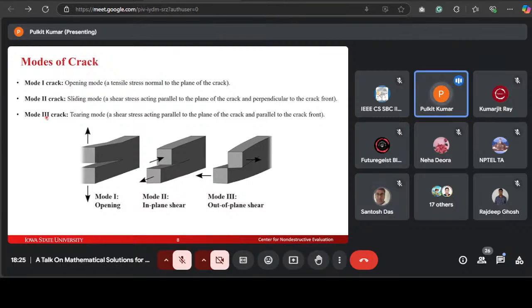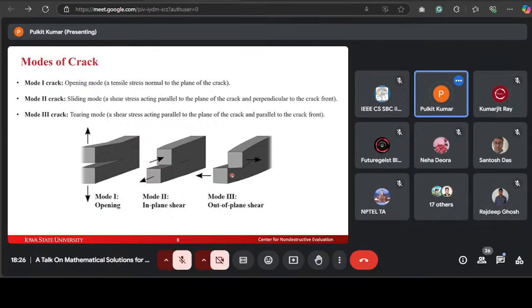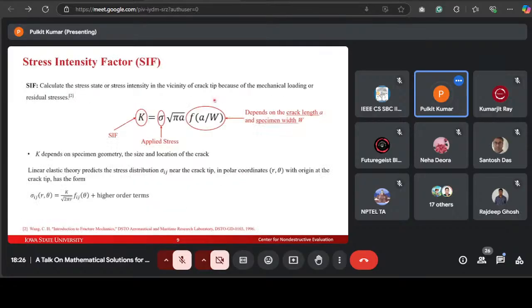Okay, so the mode 1 crack is the opening mode, and mode 2 is the sliding crack. The very important part of the crack study is the stress intensity factor. The stress intensity factor is used to predict the stress state, or the stress intensity, near the tip of a crack or notch caused by the mechanical loading or the residual stresses.